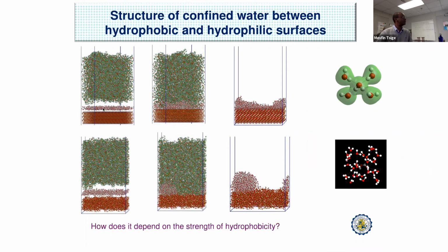So what I'm showing you over here is we have a bilayer of water. This is a bilayer, which is about 5 angstrom. The benefit of simulation is that we can control how much quantity we can have in our simulation. So I took 5 angstrom, 2 layers, confined in between. This is PDMS, polydimethylsiloxane, also a common polymer. It can be used as an elastomer and also used for contact lenses. And at the bottom, I have a solid substrate, quartz, which is also commonly used.